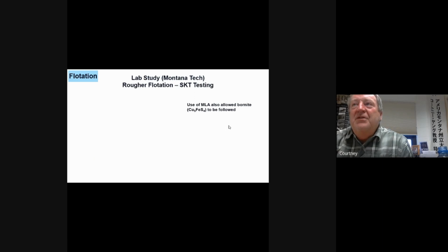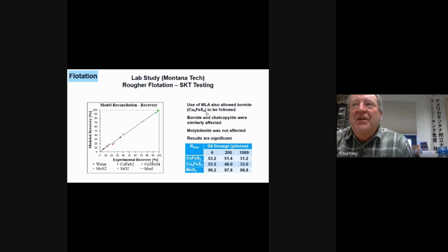Okay, so with the use of MLA, we're also able to follow bornite. Now, MLA is mineral liberation analysis. It's a technique that goes with the scanning electron microscope. So we follow these results. I'm just going to put all this up here. The bornite and the chalcopyrite gave similar results. The recovery max was 53.2. Now, this is in the first rougher float.